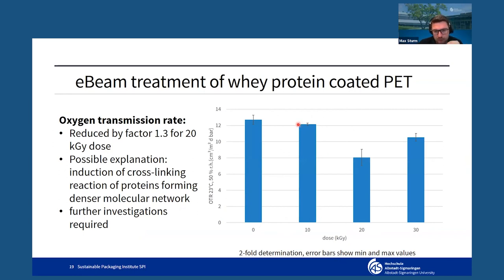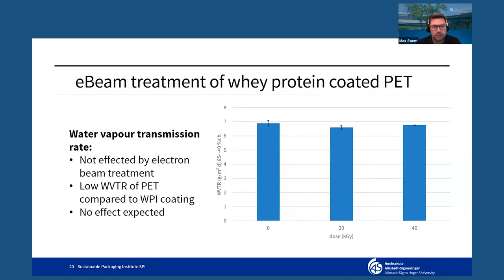As you can see here, at lower doses, here for example 10 kilograys, there's no significant impact, but at 20 kilograys there was about a 30% decrease of the oxygen transmission rate, but it was then also increasing again at higher doses. So this is probably due to the cross-linking reaction occurring here at the higher doses, forming denser molecular networks. But to be sure about the cause for this, we still have to do some more investigations. Next up, we also analyzed the water vapor transmission rates of the e-beam treated films. Here you can see the results.